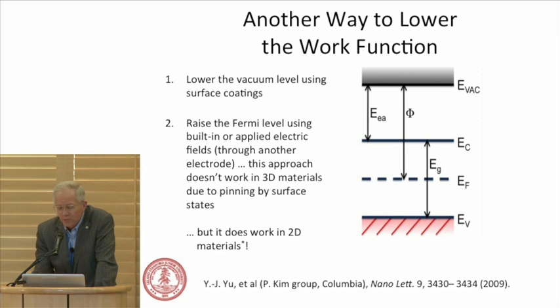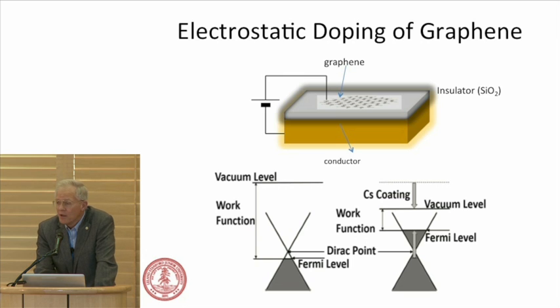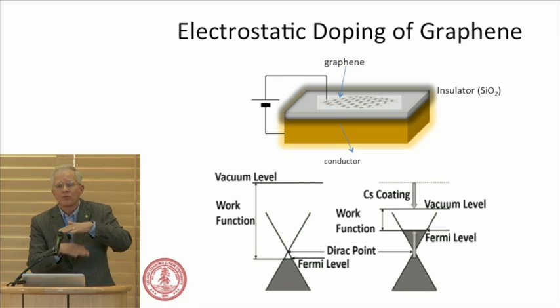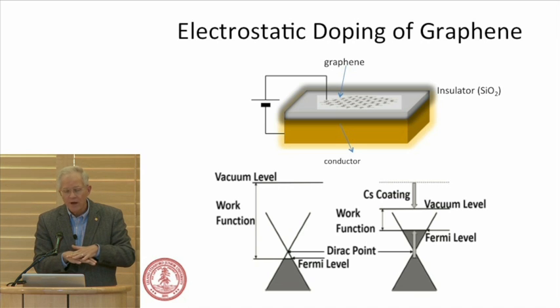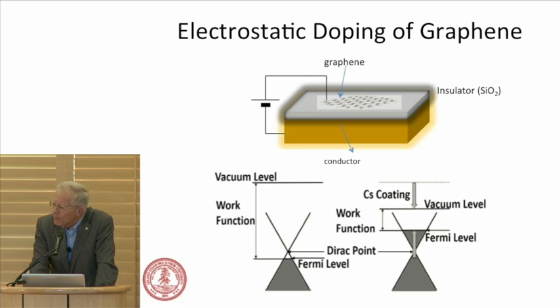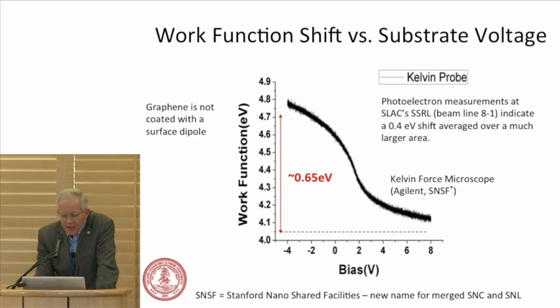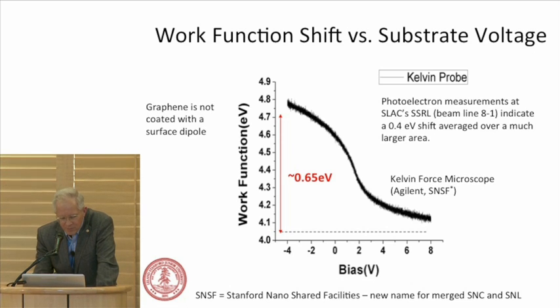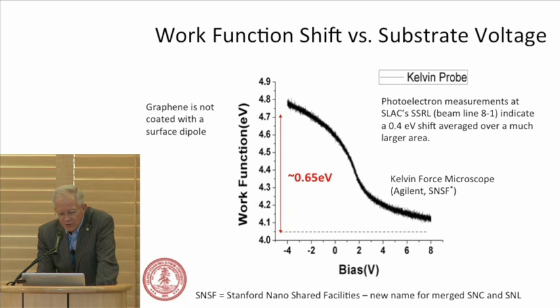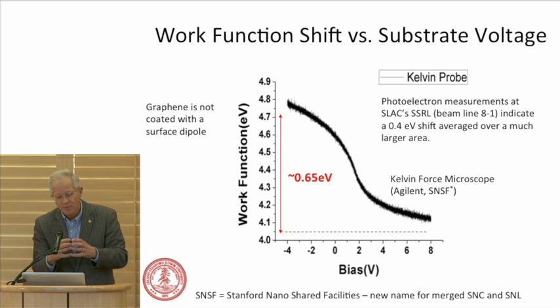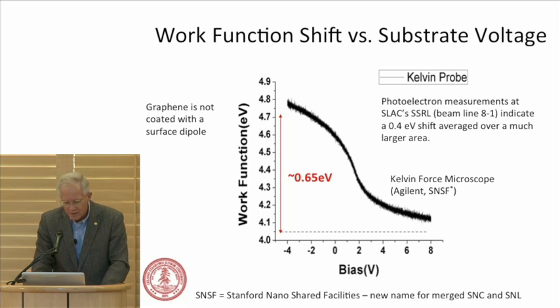In Philip Kim's group at Columbia, this was shown for transistors. So my student Hong Yuan is working on doing this for thermionics, where we would have a control through the substrate to do what we call electrostatic doping of the graphene, raising the Fermi level and lowering the work function. We've been working on this with tremendous experimental challenges to get high-quality graphene. And over the summer, Hong Yuan, using a Kelvin probe, has been able to show a very substantial shift in work function. At SLAC, we're not getting quite the same shift, but still a much larger shift than has been shown in the literature. We have a larger spot size, and the graphene isn't perfect.